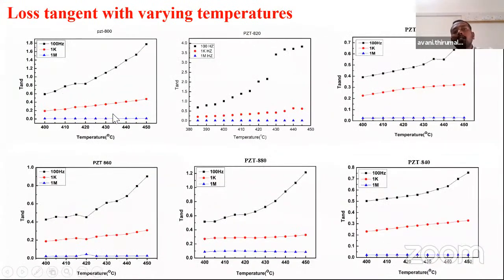This is the loss tangent. Basically, the loss tangent plays the key role in ceramics. If your dielectric constant is high and usually your loss tangent is also high, it is not applicable from the device fabrication point of view. Once your ferroelectric material has very low losses, it is perfectly suitable from the device point of view, because the losses are very, very low. PZT material has very low dielectric loss compared to other ceramics. For that, it is perfectly suitable from the device point of view in any field, like electronic devices or biomedical applications. Everywhere it will be perfectly suitable for industry applications.